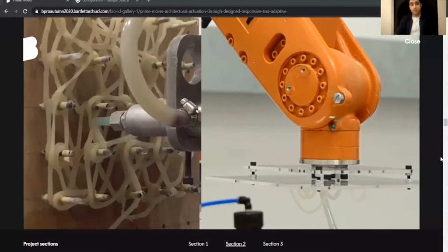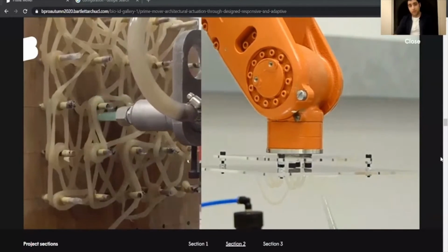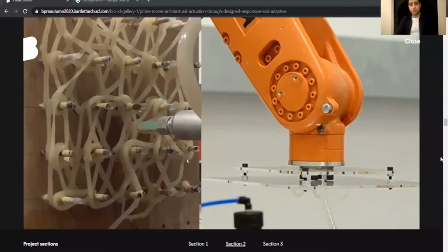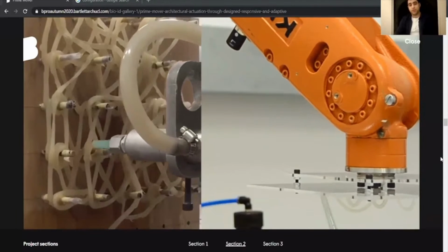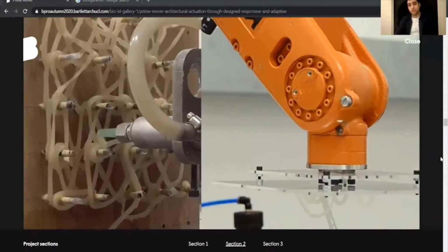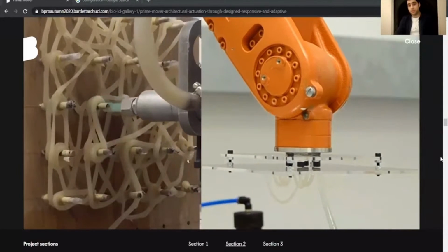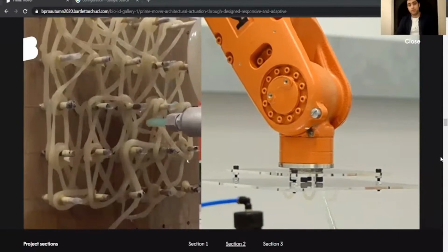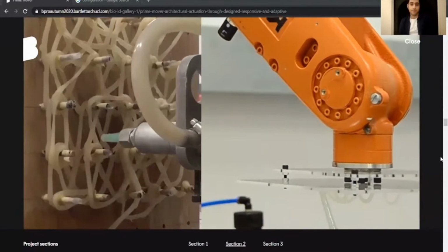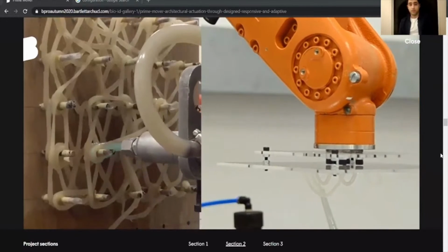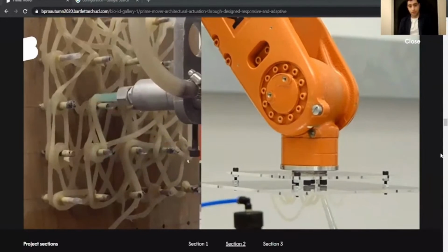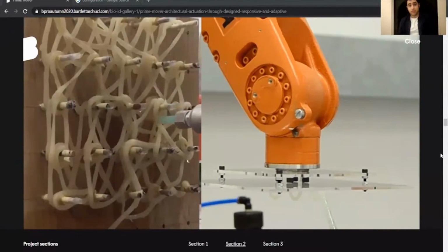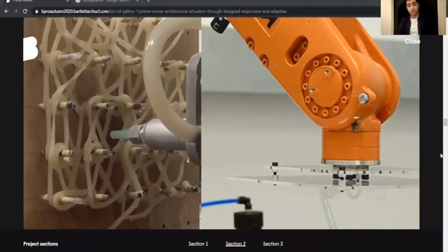However, leaving the material in a sag for a long period would cause the collapse of the woven material. In order to avoid breaking of the printed trails, we had to stabilize the material, and we did it by increasing its pH level right after extruding the ink, applying alkali on its surface. In this method, we were extruding the geometry from its cross-section, where within each scaffold pattern, we could get different iterations of weaving arrangements.